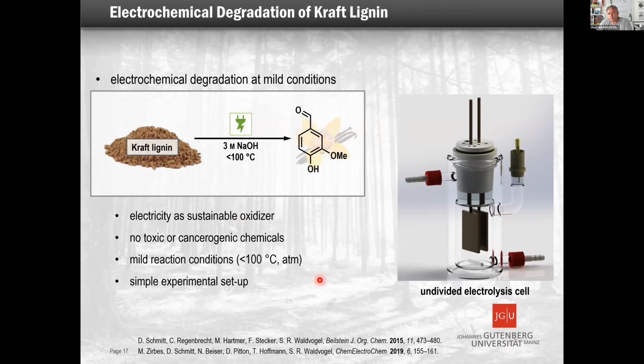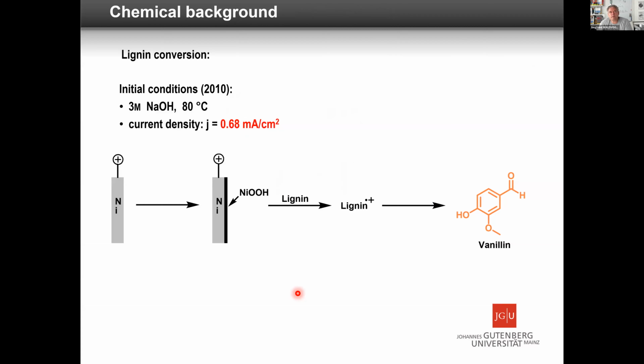Doing this by electrochemistry, we use an undivided cell, and you see it has 3 molar caustic soda. This way, it should be, let's call it, milder conditions and a simple experimental setup, an undivided cell. And it turned out, well, it's possible. We identified quite early some conditions: we use nickel electrodes, which form nickel oxide hydroxide. Then this lignin particle disintegrates and forms vanillin. You see already that these were the initial conditions.